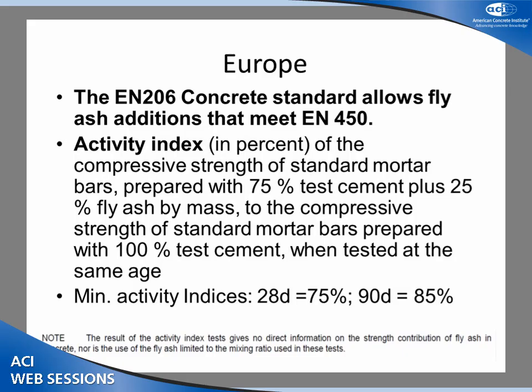It's interesting, the strength activity: EN 206, which is their concrete spec, and there's also a standard EN 450 for fly ash. Their strength activity test is pretty similar to the ASTM test. They take out 25% of the cement, put in 25% ash, and in 28 days you've got to have 75% of your strength. So, in other words, you can do nothing and still pass.